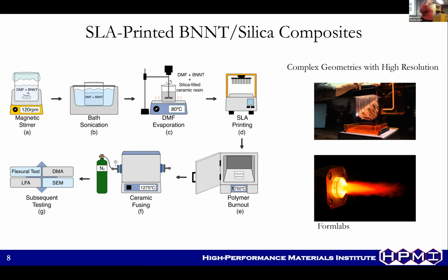But our challenge is to incorporate these nanofillers into the inks, so you have a nanocomposite rather than just the ceramic. We want to have those nanoscale toughening and the nanoscale thermal spreaders as well. So this will help with high temperature applications. So we put it in DMF, magnetic stir, bath sonication to break up the BNNT clusters to be able to get a really good dispersion. Put in the silica filled ceramic resin. This work was done with silica, fused silica as the ceramic. This is not a super high performance, I would say it's a middle performance ceramic.